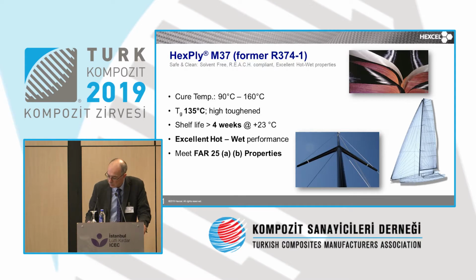I will focus on three of the latest innovations, which first of all is the M37. The M37 has a cure temperature between 90 and 160 degrees Celsius, a TG of 130, 140. The toughness is quite interesting. The shelf life is superior to 4 weeks. And the hot and wet performance make it a good candidate for various applications and also marine applications. But it's also today considered for automotive structural parts.